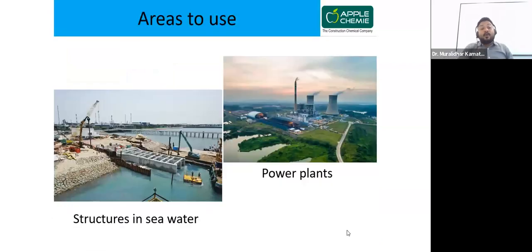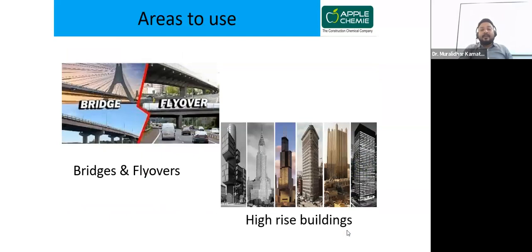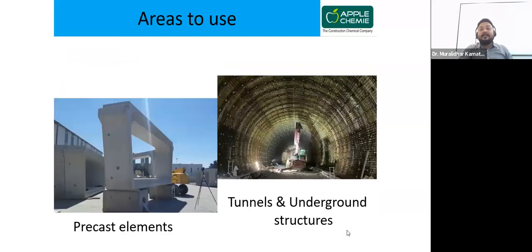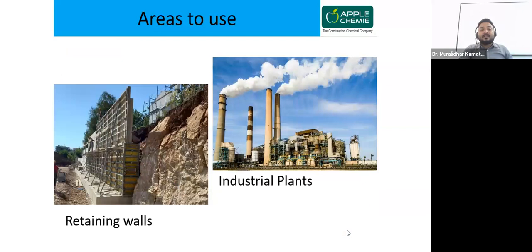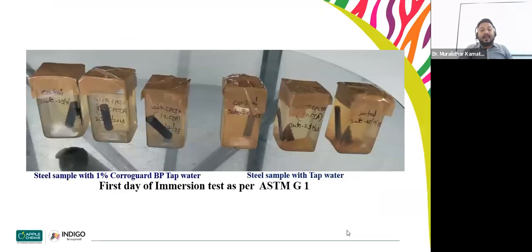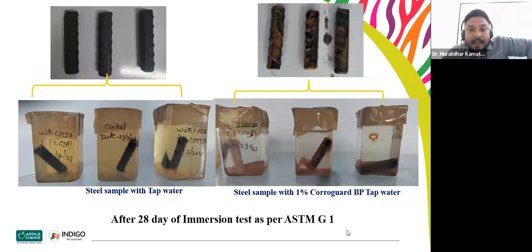Where to use our corrosion inhibitor solution: structures in sea water, for sure it is recommended; power plants, bridges and flyovers, high-rise buildings, precast elements, tunnels and underground structures, retaining walls, industrial plants. And here you can see the test we did with a steel sample with 1% corrosion inhibitor in tap water, and a steel sample with tap water only, that is without it. Here you can see after 28 days how the corrosion initiation looks without and with.